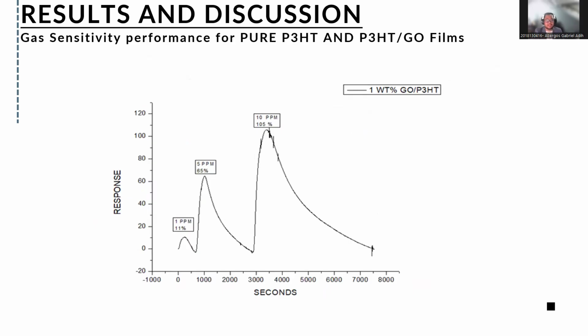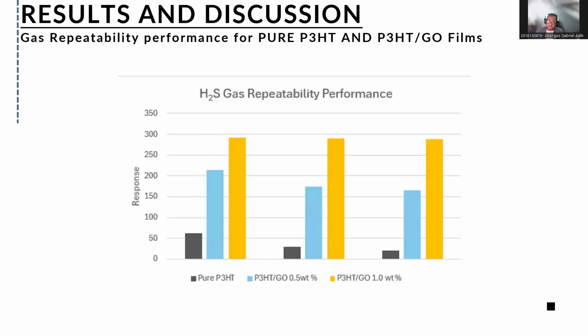But there is a big change when we add 1 weight% GO. As you can see, at 1 ppm the response is already at 11%. Then at 5 ppm, it jumps to 65%. And at 10 ppm, it reaches 105%. So the big improvement means that more GO helps the sensor a lot. GO adds more active sites and improves how well the material detects gas. And this makes the gas sensor much more sensitive.